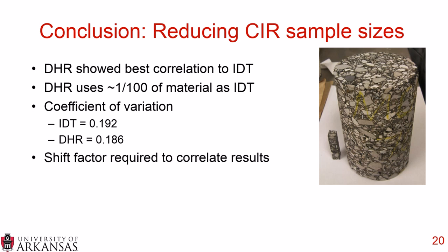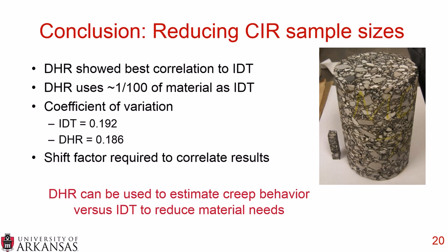However, we did need that shift factor to correlate the results between the DHR and the IDT. So in summary, we found that the DHR can be used to estimate creep behavior versus the IDT to reduce the material needs for testing in the laboratory.